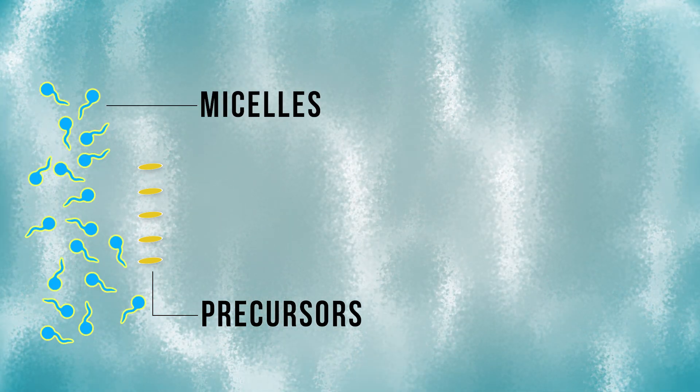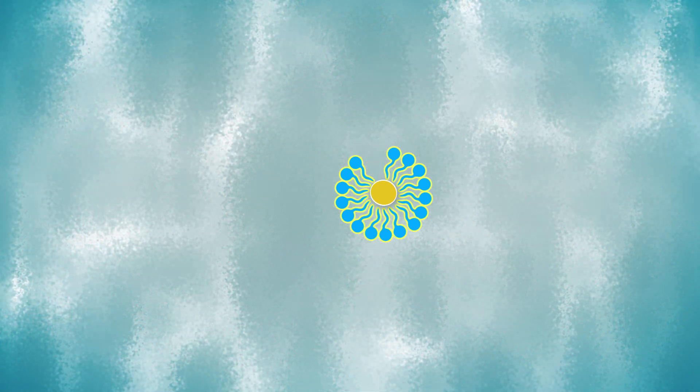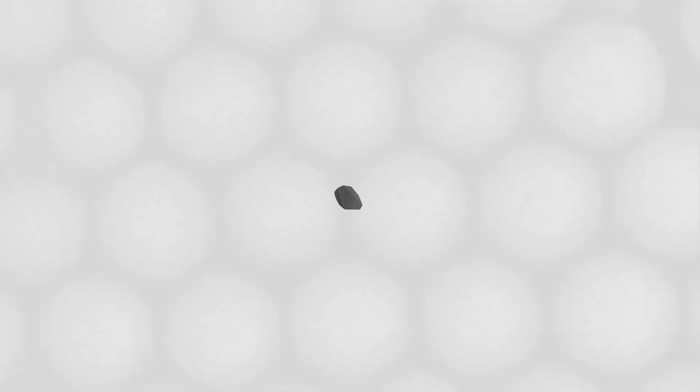The whole process is very simple. When the detergent dissolves in water, it forms micelles and the hydrophobic precursors automatically get drawn into the hydrophobic cavities of the micelles. Crystallization then occurs within that confined environment, forming very well-defined morphology with controlled size.